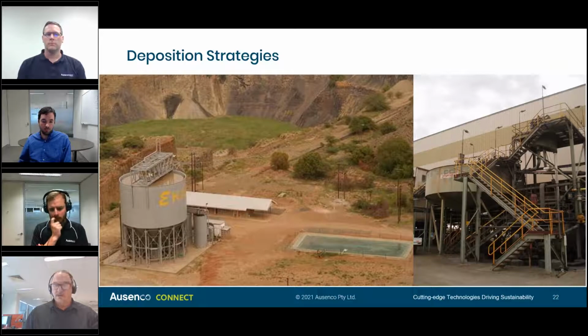This particular slide is basically the ability to pump your tails to voids or mined out pits and perform the thickening duty quite close to the pit to avoid the high cost of pumping thickened yield stress material. So this material is dropped into the pit just to the north of the thickener. And on the right, one can see the options of what can happen. You could consider cyclones ahead of your thickener, and in this particular instance, the cyclone overflow reports to the thickener, and then both the cyclone underflow and thickener underflow would be pumped out as a thicker yield stress material.